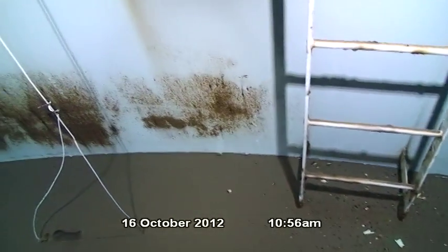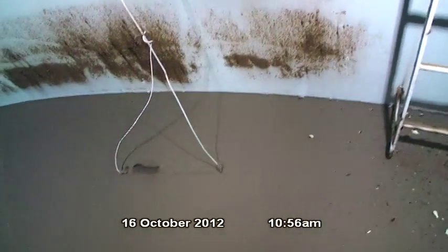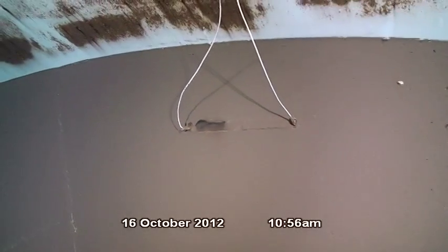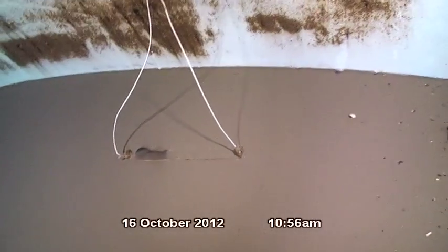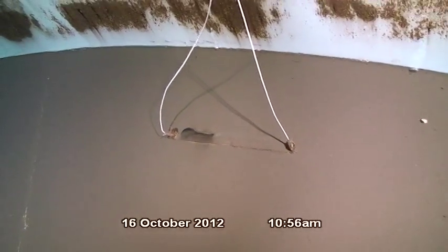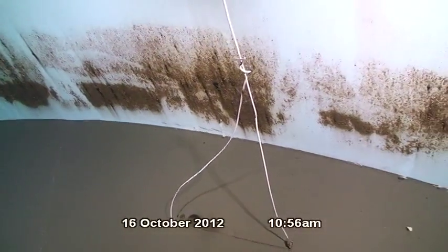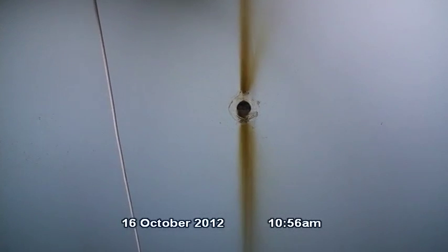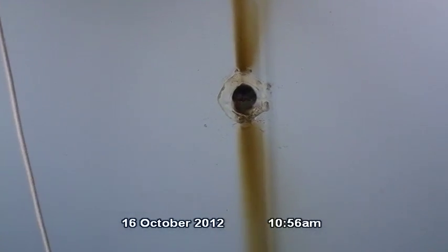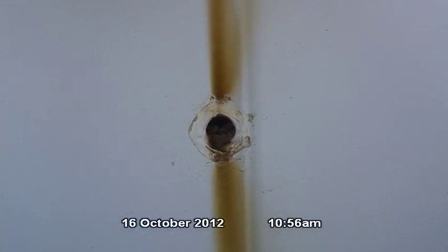Corrosion is also present where the target guide wires are attached to the target base and where the target base is welded to the floor. The target base is coated with epoxy. The guide wires are attached to the base of the target, but one guide wire has been severed approximately 2 feet from the target base. Moderate to dense corrosion is located on the interior of the level sensor sampling line. The line appears to be approximately 50% obstructed with corrosion.